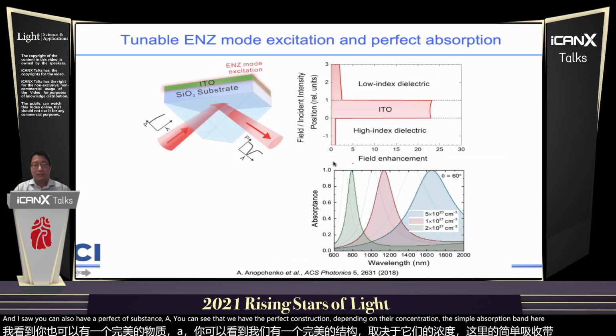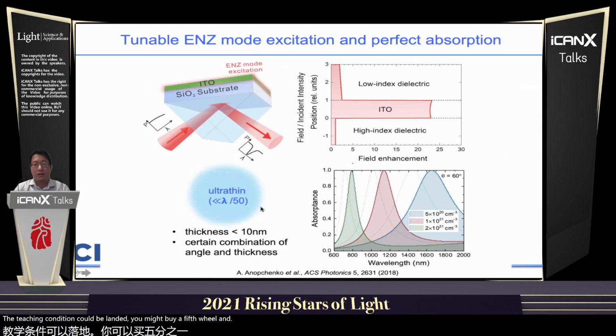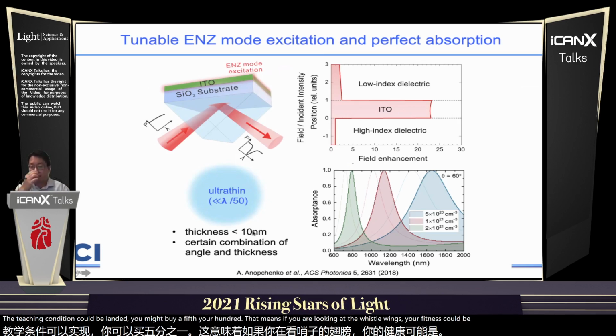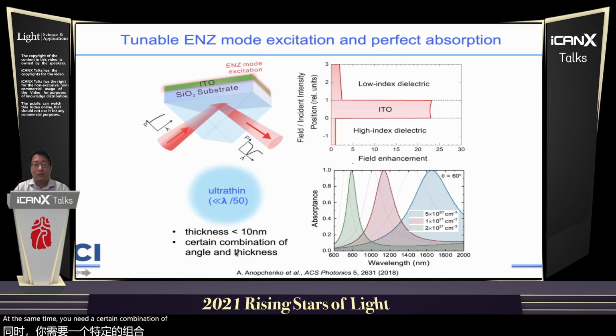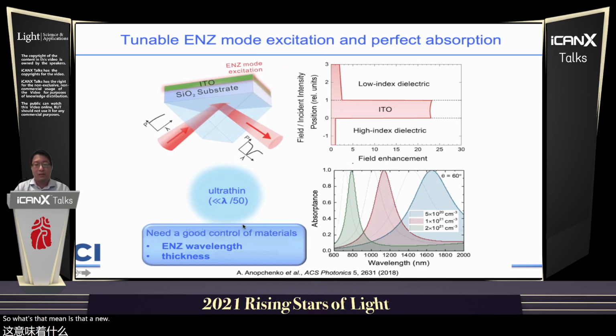And just keep in mind, to excite this mode, you can actually use a really thin film. The excitation condition could be lambda divided by 50 or 100. That means if you are looking at the visible range, your thickness could be only 10 nanometers thick. At the same time, you need a certain combination of angle and thickness in order to excite this mode efficiently. So what that means is that you actually need really good control on the material in terms of the ENZ wavelength and thickness here.